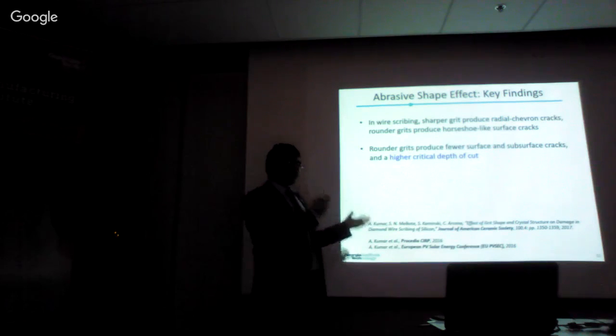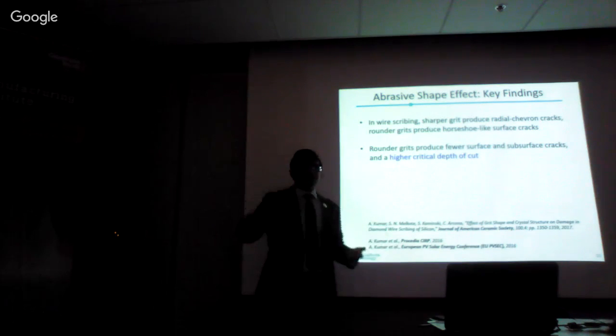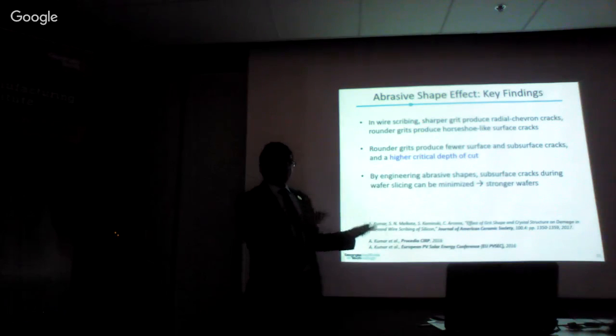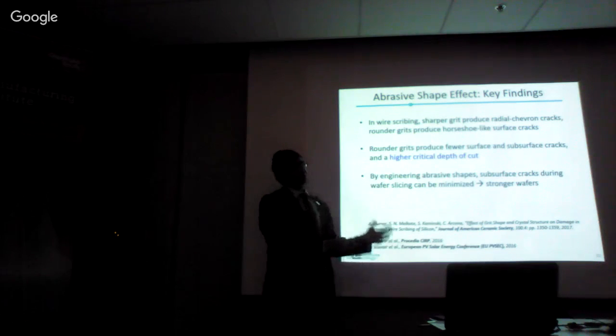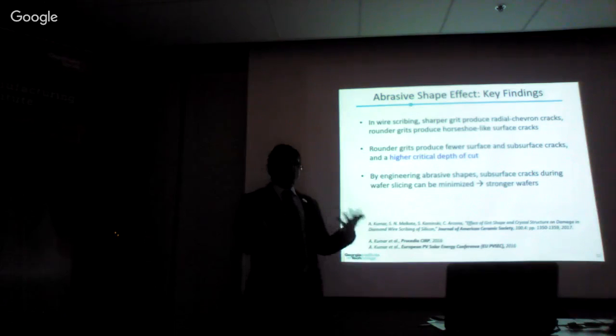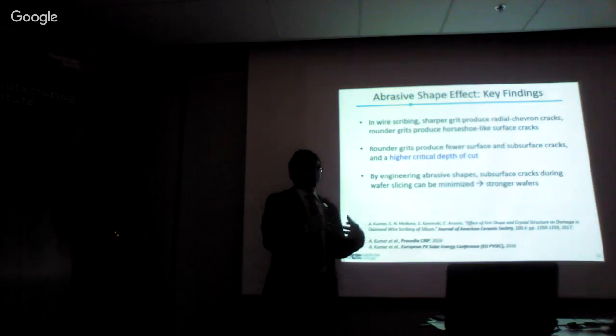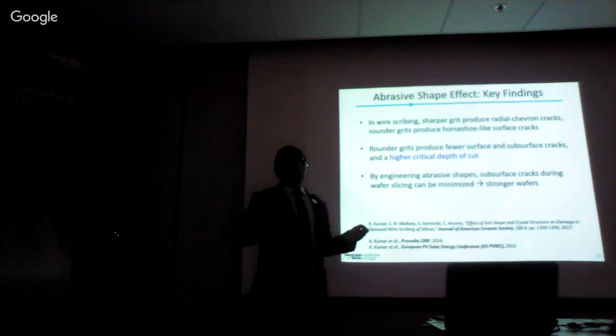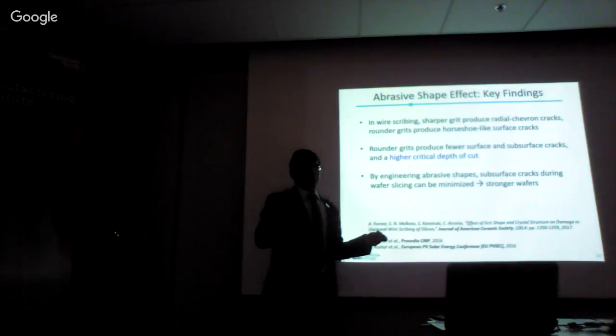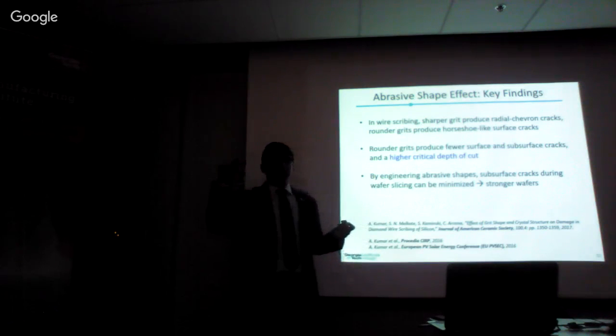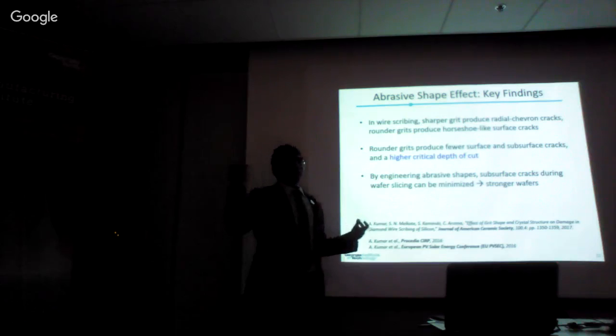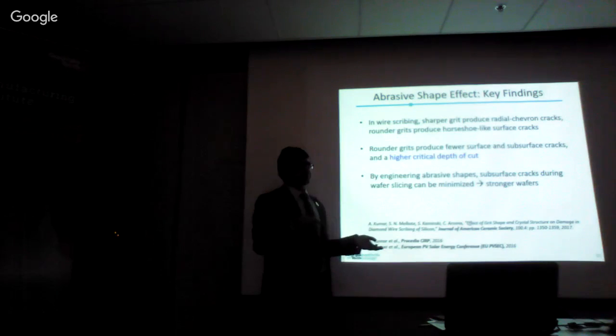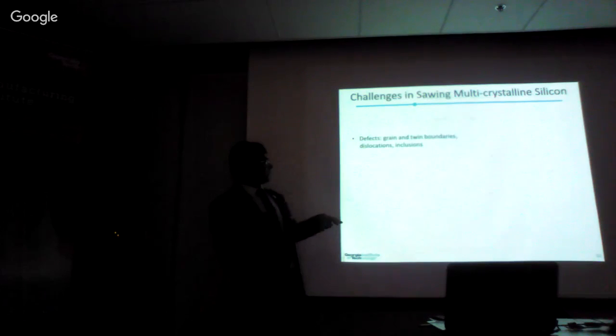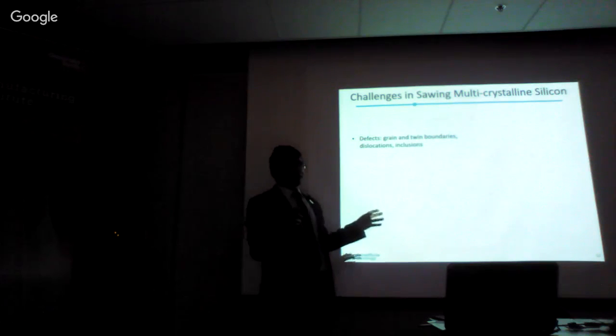Now, how do we take this result to the actual diamond wire sawing process? So the implication of this research is we can engineer the grit shapes to have more rounded abrasives and reduce the subsurface and surface cracks in wafer slicing, which can increase the strength of these wafers and thus reduce the thickness of these wafers, reducing the cost of solar cells. Moving on to the next slide, the next task, the effect of multicrystalline silicon.